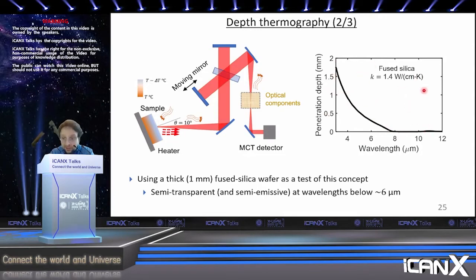It also has relatively low thermal conductivity, which means that we can expect to see, even in this simple geometry, a temperature gradient from the top surface to the bottom surface, because you're going to have a temperature drop due to this relatively low thermal conductivity. And so this is the very simple setup and sample that we use to demonstrate this thermal imaging, if you like, or thermal characterization as a function of depth.